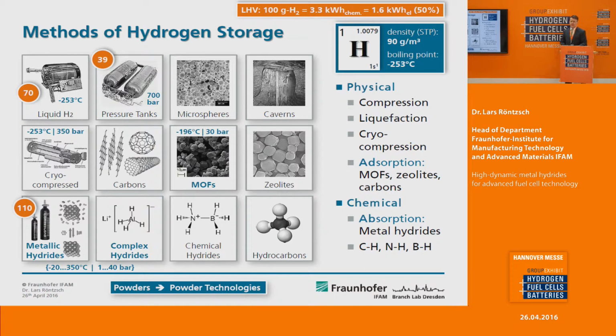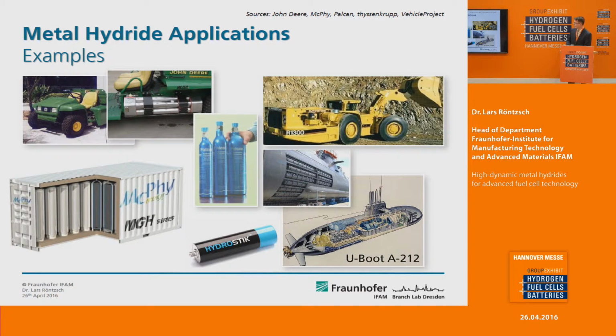When we look at this slide, I've compared some physical parameters of different hydrogen storage technologies, and you see in the orange fields the volumetric capacity of the two classic forms of hydrogen storage, liquefied and compressed gas at 700 bars. And below that, we have the hydrogen storage capacity in metal hydrides. And you see, we usually get more than 100 gram hydrogen per liter of volume, which is a very high amount. Well, applications where metal hydrides are already used are shown on this slide.